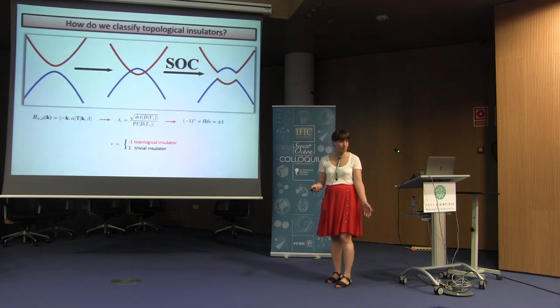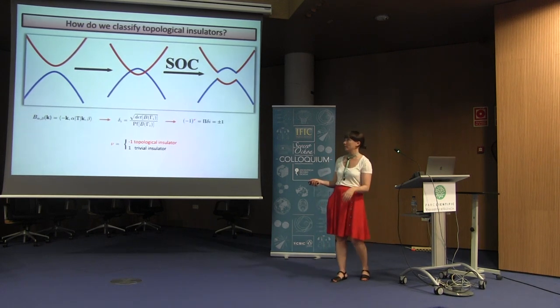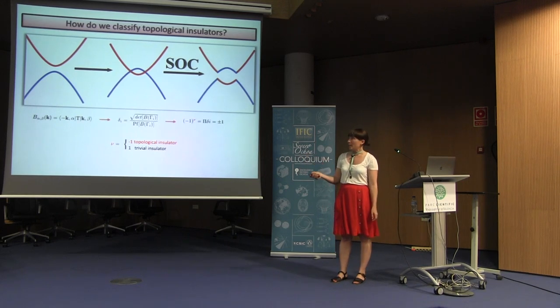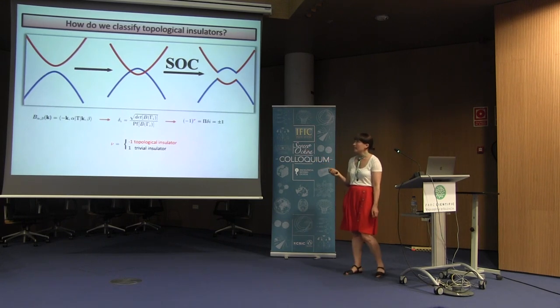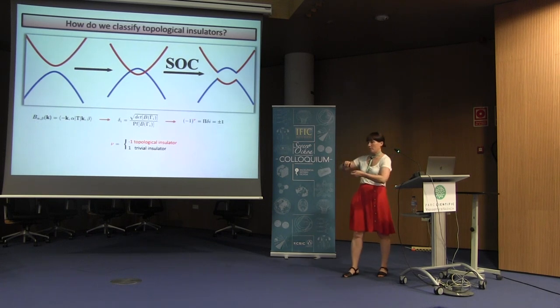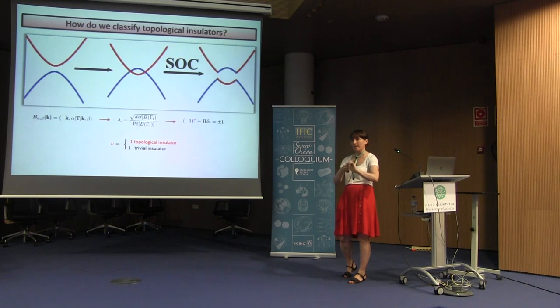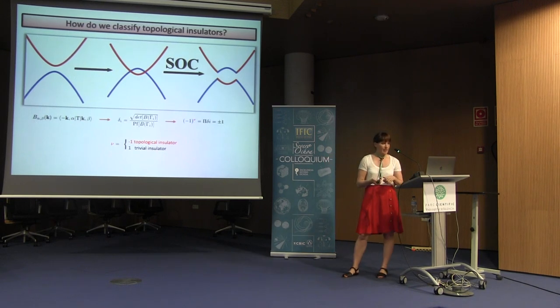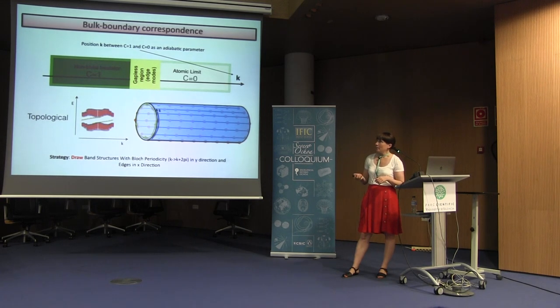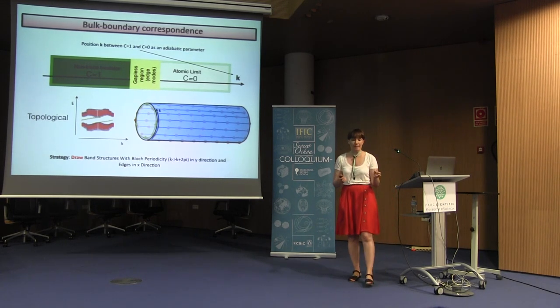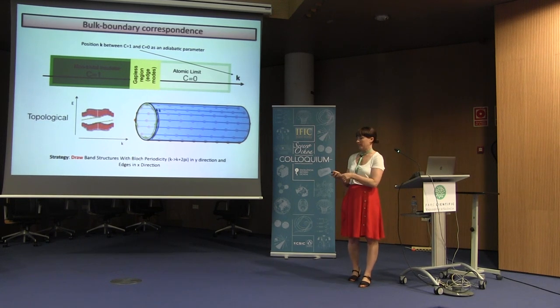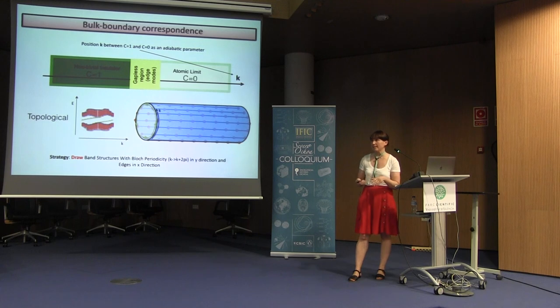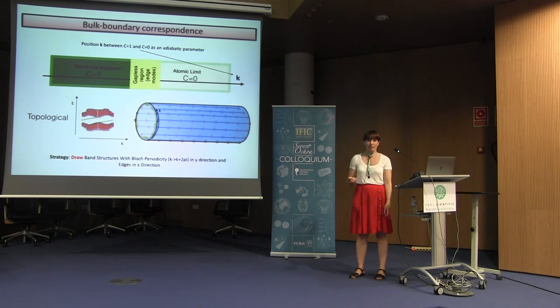the band spectrum of a material given by the energy as a function of momentum k. If we have a strong spin-orbit coupling, what happens is that the energy levels are shifted, and one goes below, the other one goes up, and in the end, the result is that we have an inversion of the bands. When we have this inversion of the bands, we can have a topological insulator, because our bands somehow are twisted, and this twisting has created the inversion of the eigenvalues. In a topological insulator, they are insulating in the bulk but conduct electricity on the surface. It's called bulk-boundary correspondence.